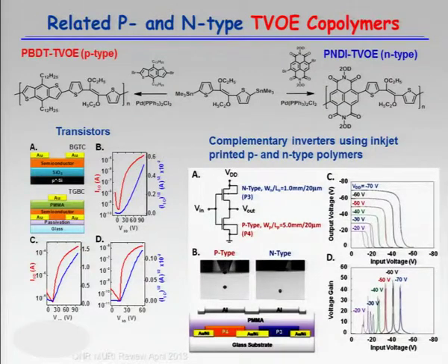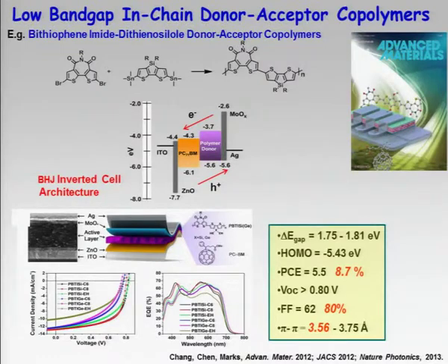We've made lots of other devices. Polyera, which is our spin-off company, has made structures now with 1 million transistors. And this one happens to be by inkjetting. And you can see quite reasonable performance, completely air stable, all processing under air. So if you're really good at getting the mobilities out of these polymers, tuning the band gap, you can do this. And this is the final polymer slide I want to show.